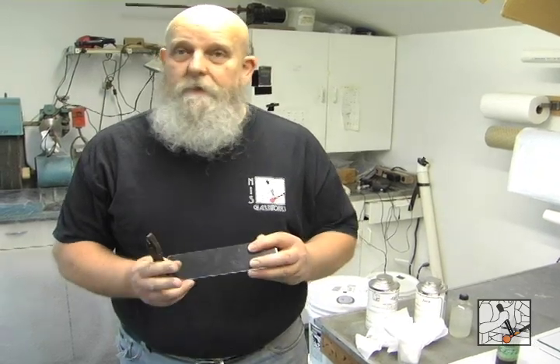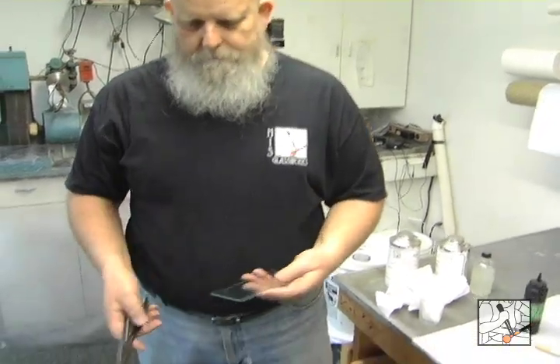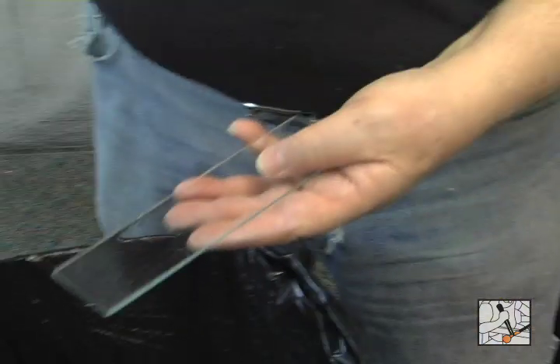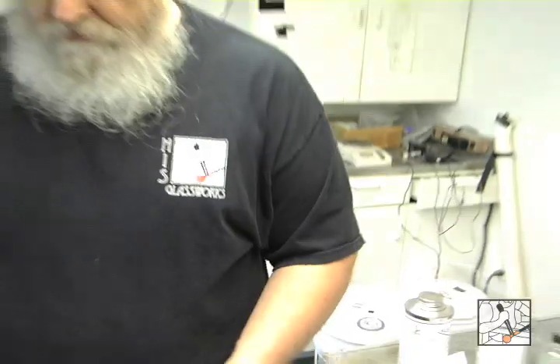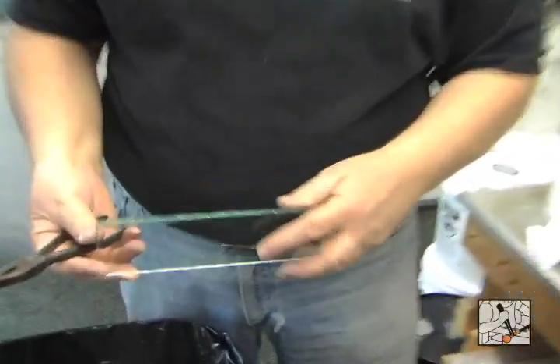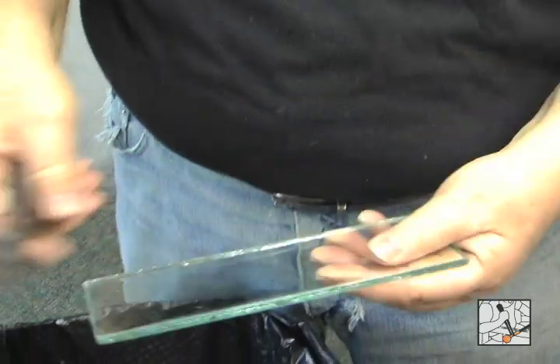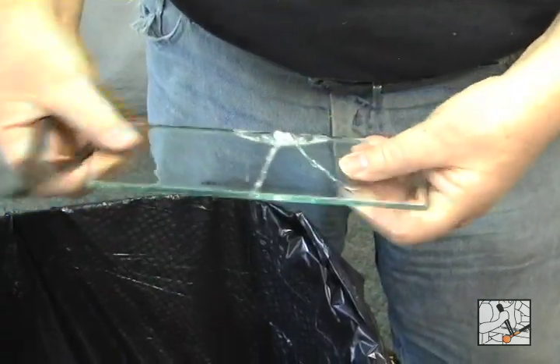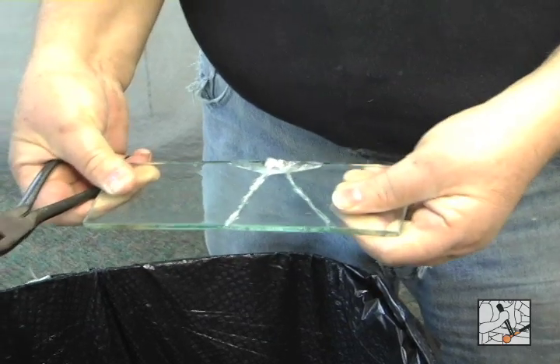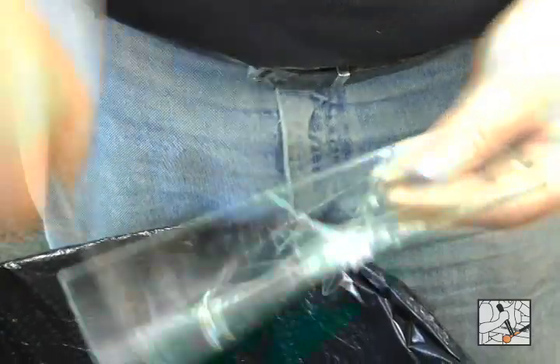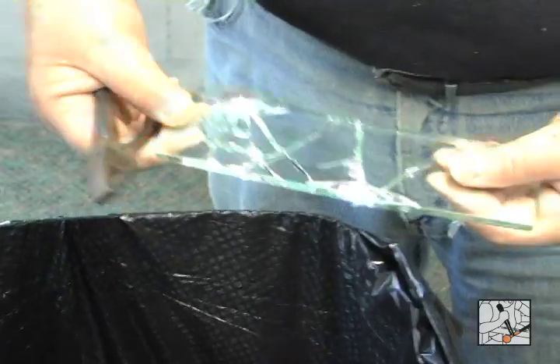Just to show you, this is the piece that I coated yesterday, not fully cured, and it's only coated on one side. Still works, but it's just not as strong. This piece was coated many days ago, also a quarter inch plate glass. It's stronger, you can't pull it apart, but this is why you want it.